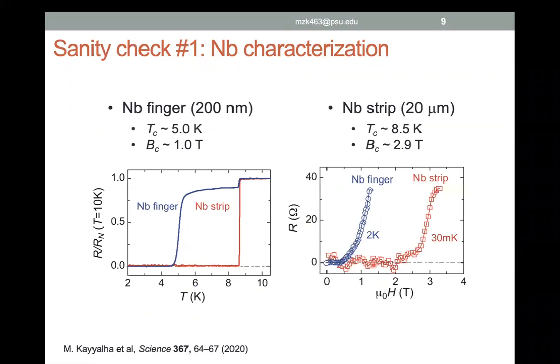So now, after I made this device, I did a bunch of sanity checks. So the first sanity check was, I have niobium, is it superconducting? So I looked at the niobium strip and niobium finger. The niobium strip is wider, so the TC is around 8.5, BC is around 2.9. Niobium finger is much narrower, so the TC drops to around 5, BC drops to around 1 Tesla. So conclusion here is my niobium is superconducting.